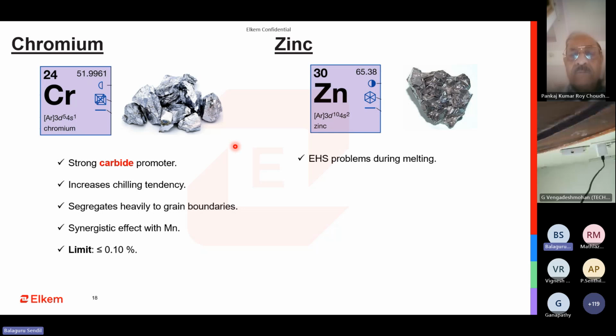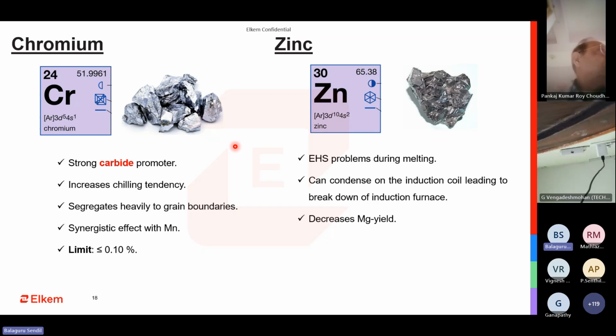Zinc, we know, is coming because of coated scrap. It is an environmental health problem. When you're trying to melt it, it is going to give a lot of fumes. It can condense, and people with a refractory lining background know that when a bit of zinc comes in, it can spoil your furnace lining and lead to furnace breakdown. When you have zinc, it also spoils the magnesium recovery. So these two things are going to be associated with steel, and this can actually cause real damage to your foundry.